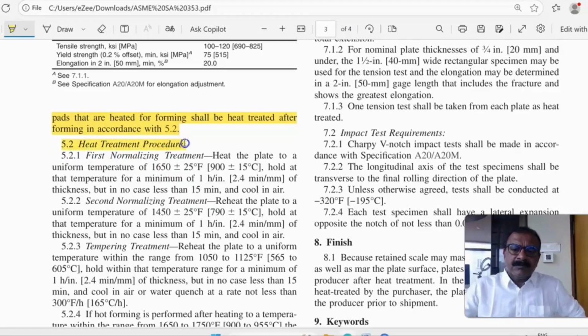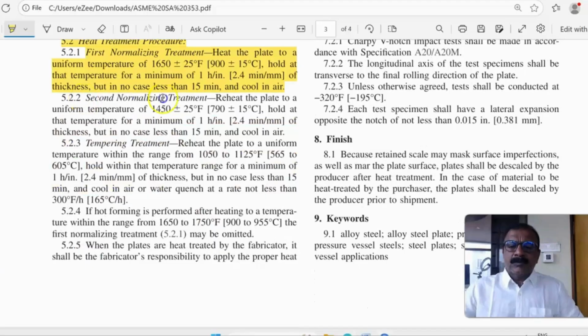Heat treatment procedure. First, normalizing treatment. Heat the plate to a uniform temperature of 900 plus or minus 15 degrees centigrade. Hold at temperature for a minimum of 1 hour per inch of thickness, but in no case less than 15 minutes, and cool in the air. Then second normalizing treatment. Reheat the plate to a uniform temperature of 790 plus or minus 15 degrees centigrade. In first normalizing, we heated up to 900 plus or minus 15, but in the second one, it is 790 plus or minus 15, and hold at temperature for a minimum of 1 hour per inch, but not less than 15 minutes, and cool in the air.